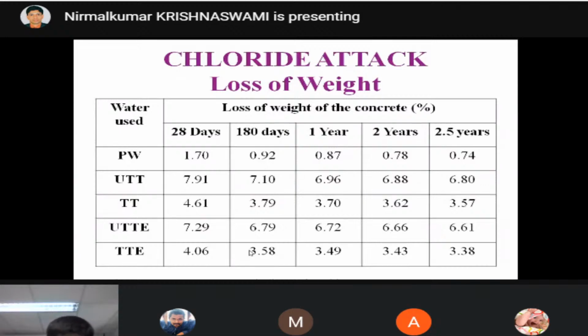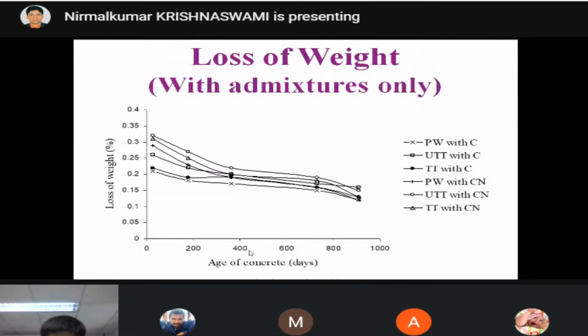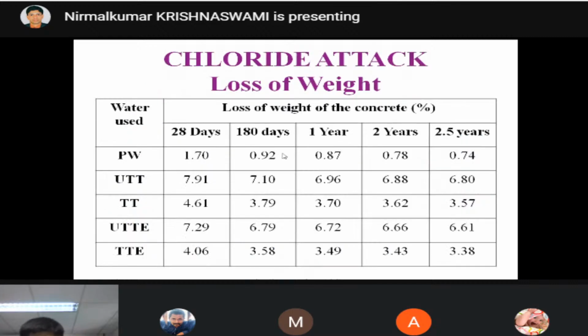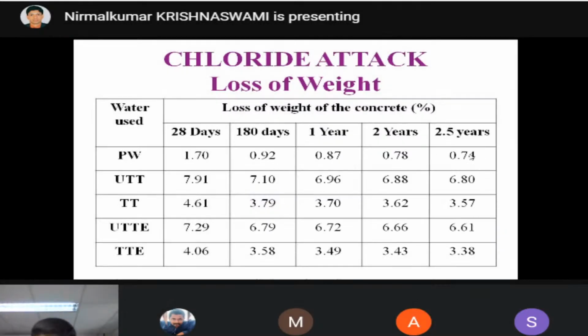Just you see the next results for when adding the admixtures. When adding the admixtures, the reduction in loss of weight is less than 0.35 percentage. Here, if you see, minimum, I think this we can take. In this table, 0.74 percentage is the lowest for 2.5 years.